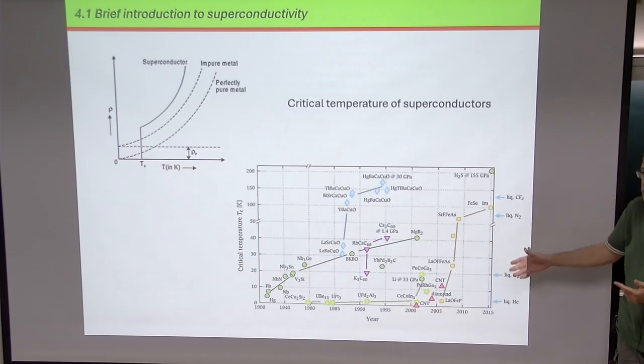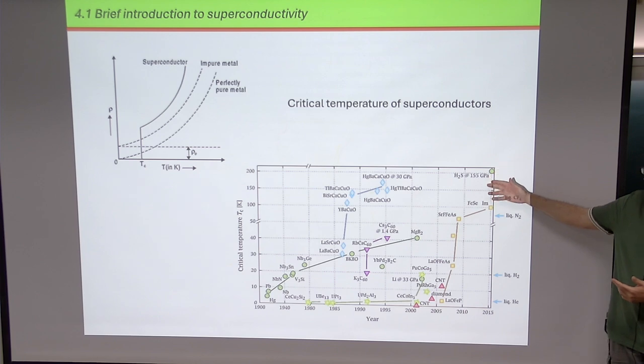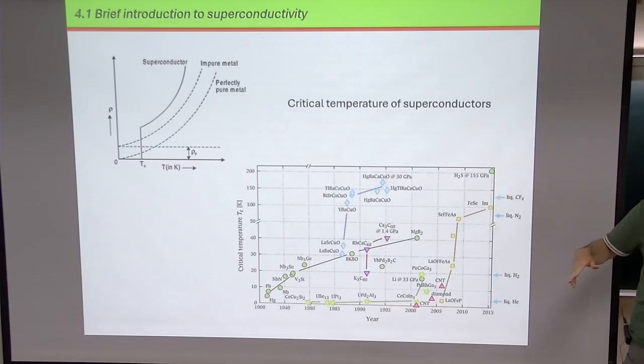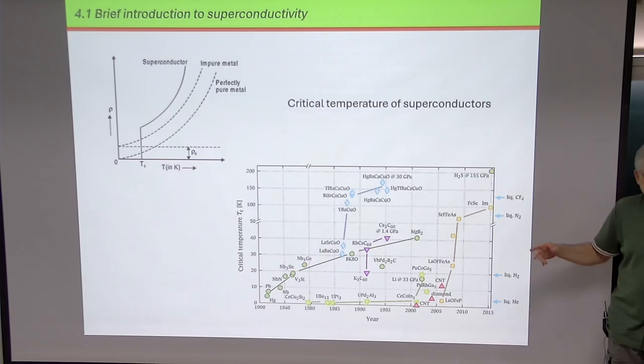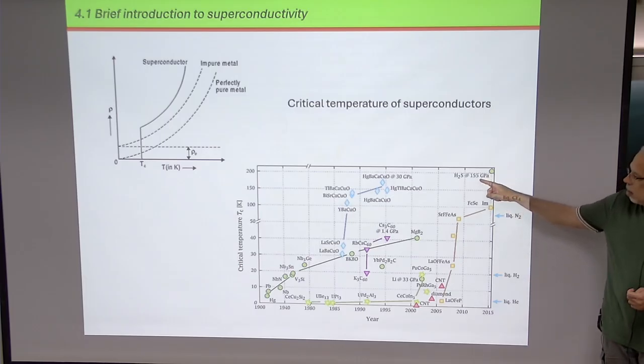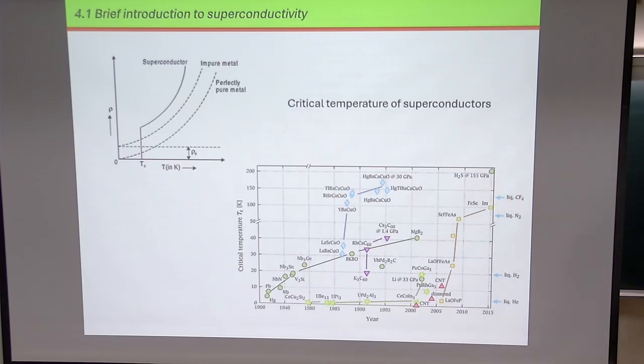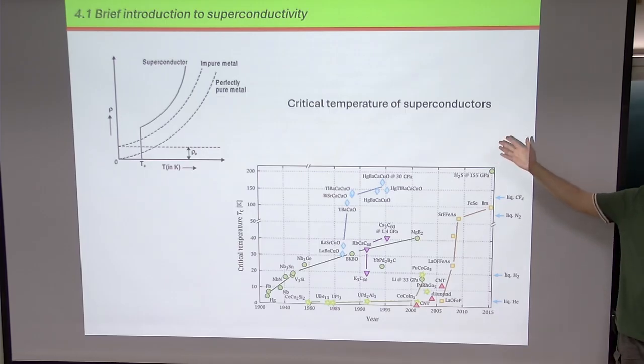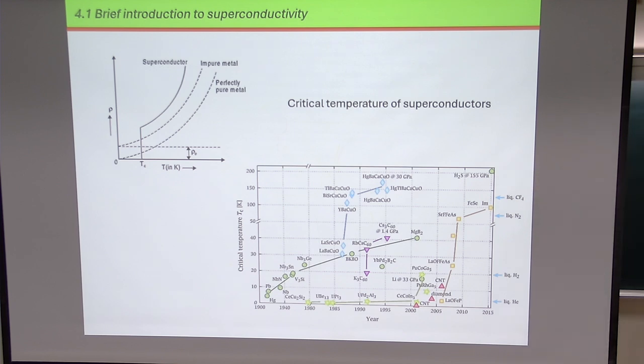Oh, this is just a table with a few of these elements, but there are many other elements in between. I think right now, this is at 155 gigapascals. It's 200 Kelvin, which is not so cold. It's still cold for us, but not so cold. And 155 gigapascals is what you have to apply, so it's a huge pressure. And you can go higher. I think the record is really close to room temperature, but you also have to put a lot of pressure. But yes, in fact, there have been reports of some room temperature superconductors.